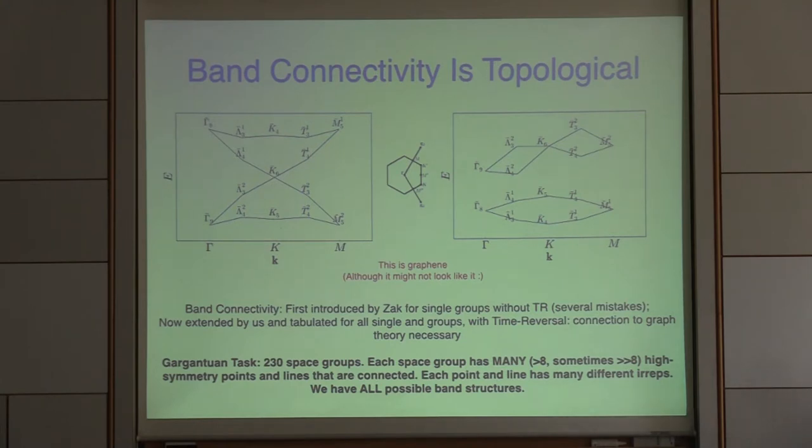So all I've done is just symmetry, momentum space, and in fact some of the alternative classifications that exist in the literature miss this example if you don't have inversion symmetry, for example. So if you don't have inversion symmetry, some of the classifications existing in the literature would characterize this as trivial, which is not true, because graphene without inversion symmetry is still topological.